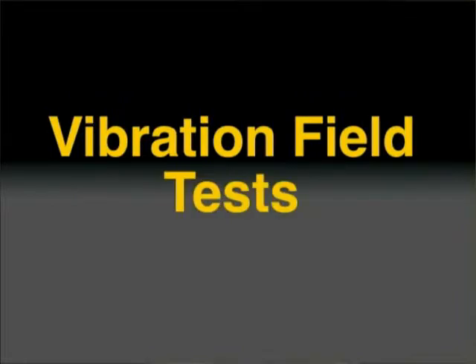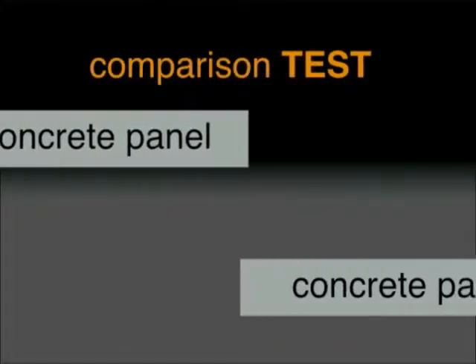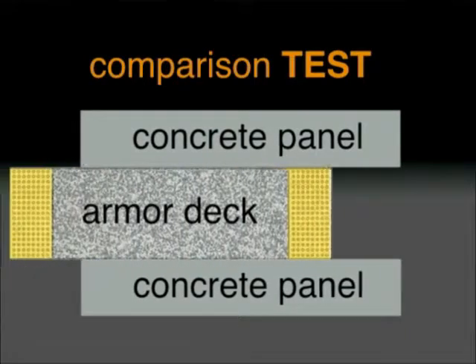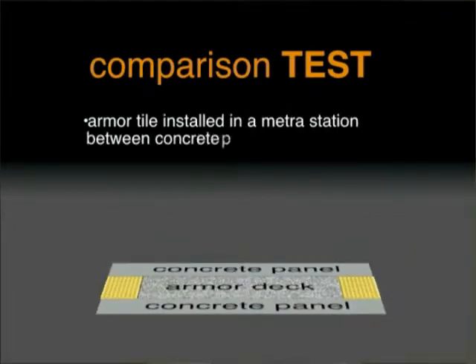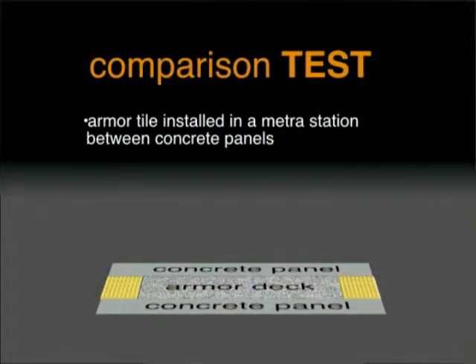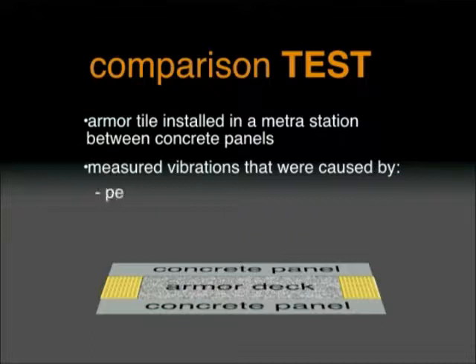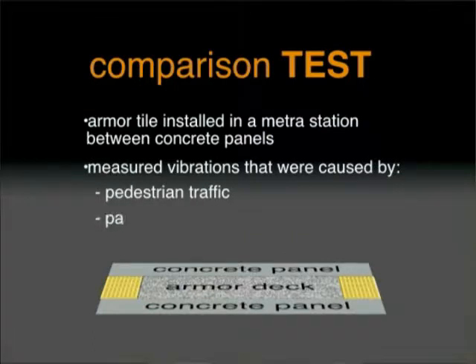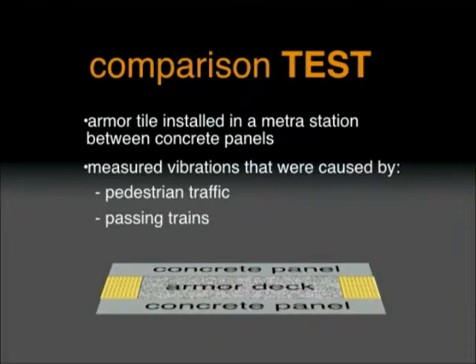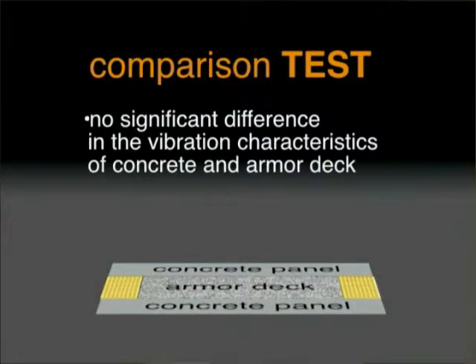One test that we did in the field was a side-by-side vibration comparison test on a Metra station in Hazel Crest, Illinois. Engineered Plastics had installed one of their armor deck panels in a Metra station that was planned for renovation. They installed it in between the existing concrete panels. And I went to that station and I measured vibrations that were produced by people walking over the panels, and vibrations produced by passage of a train to demonstrate the difference in the vibration between the armor deck and the concrete panels. The results of that test indicated that there was no significant difference in the vibration characteristics. The train passage produced essentially the same magnitudes of vibrations on the concrete panels as the armor deck panels.